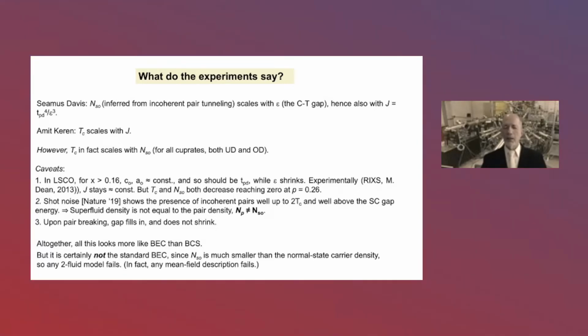And altogether, all this that I have just recounted, it looks certainly much more like BEC than like BCS. But I want to emphasize that it is definitely not a standard BEC either, because in that theory and in any two-fluid model, at zero temperature, you have quenched all the excitations, so all the normal state carriers must be in the superfluid. But that's not experimentally the case. So any two-fluid model failed. And in fact, any mean field description failed.